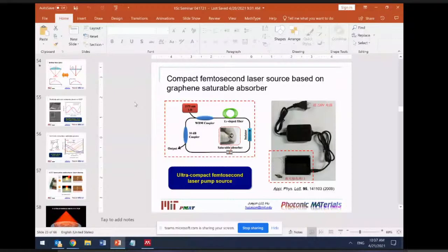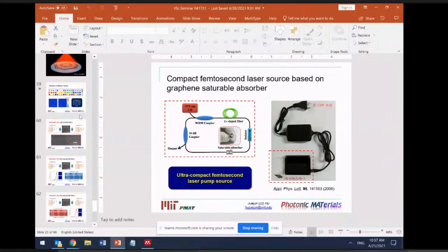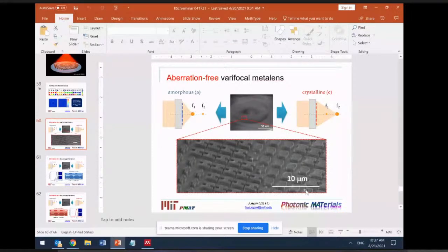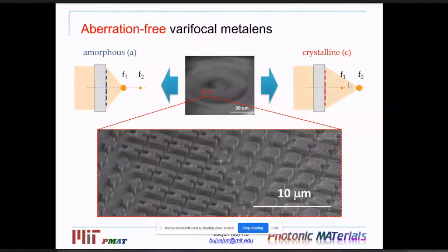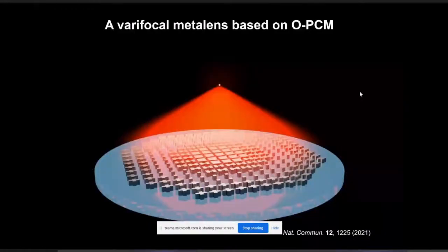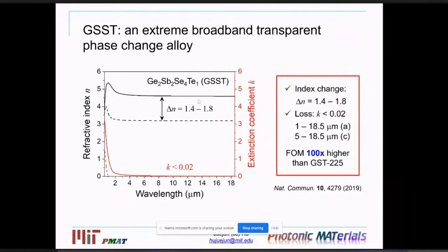Okay. And for these varifocal lenses, the lens is in the reflection mode, right, if I understand from the figure? Oh, this one is actually in the transmission mode. We fabricate it on a transparent substrate, so the light can pass through. Okay, and when it transfers from amorphous to crystalline structures, what is the change in delta K? Because that will absorb the light, right? Yes. That's why we are using GSST instead of GST, because we operate at about 5 microns, and the change of K is actually quite minimal. The K at 5 micron, I believe, is something like 0.0. It's at the measurement error, technically within the error bar. That's why we have very little loss here. It's bi-state transparent. Okay, thanks.